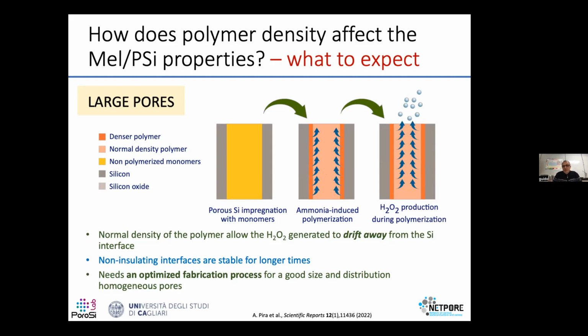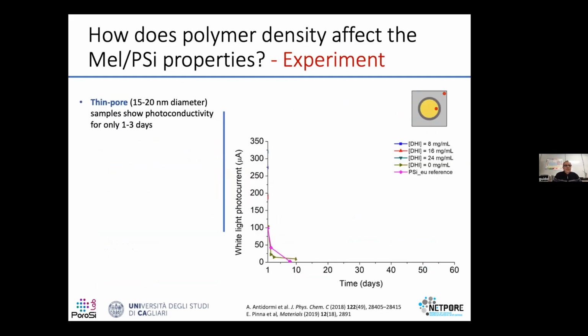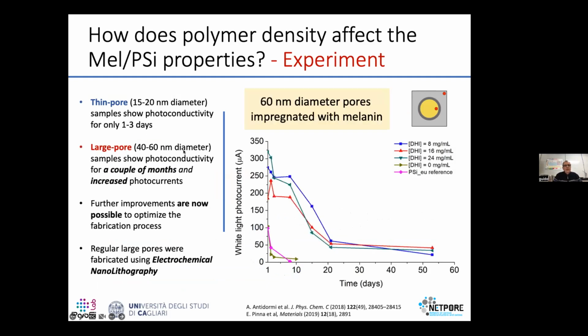So with this model, which implies an understanding of what the polymer does at the nanoscale, we made some tests. This is what happened with tiny pores. We are looking at the photocurrent intensity over time, and you can see that after a couple of days, it goes to 0 with tiny pores. When you go to a larger pore, the difference is quite remarkable, since you have a significantly higher photocurrent, and you may still have measurable photocurrent after about 2 months. This means that since you have a stable system, you can also try to optimize your system better.